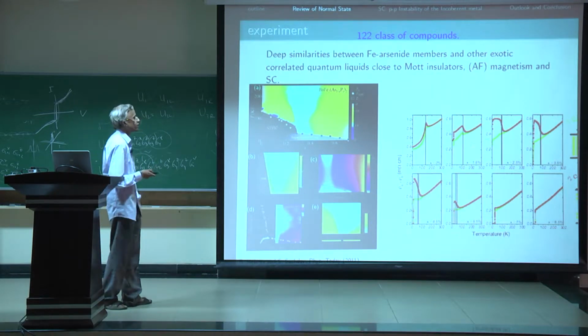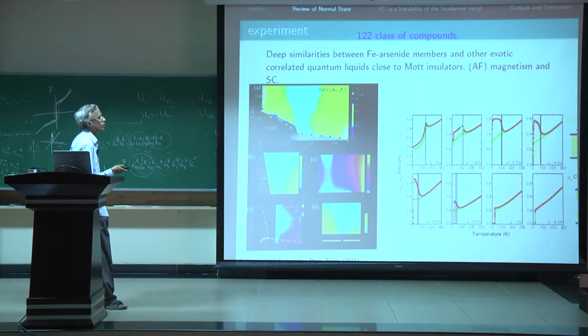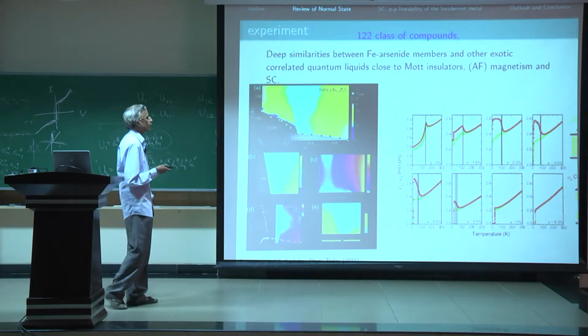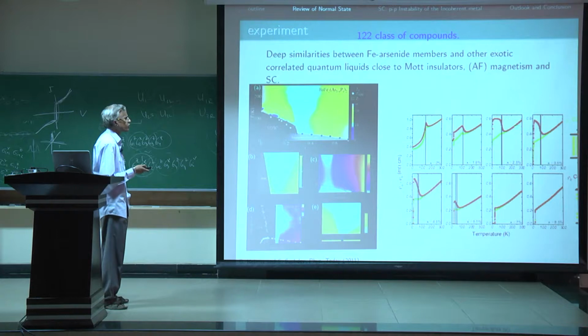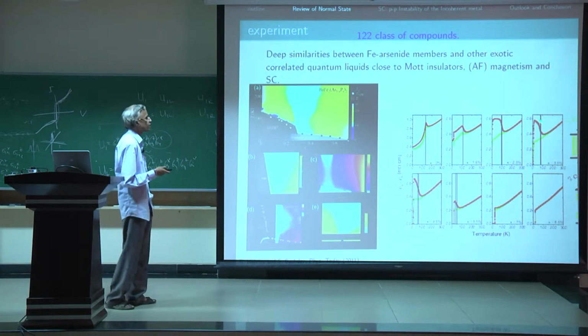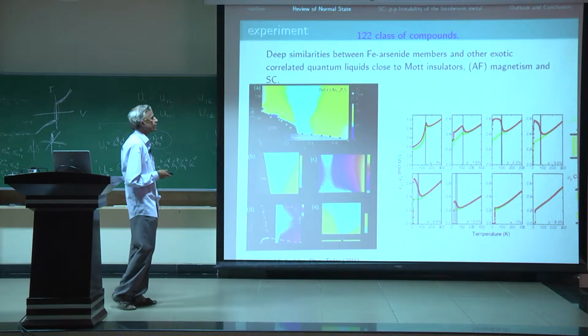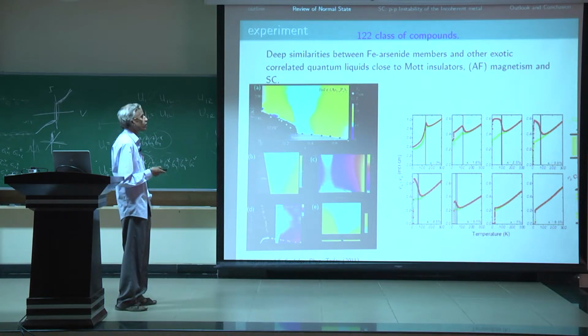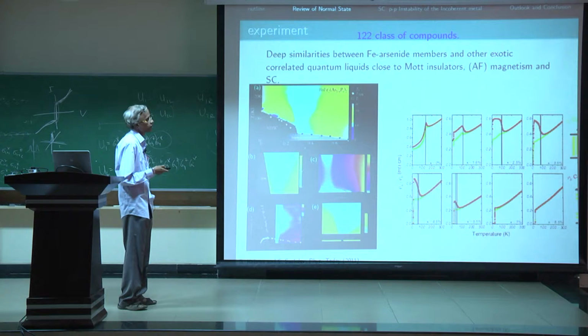In particular, what you see is that along the shorter direction, remember I told you that B is smaller than A in the orthorhombic structure, nevertheless the resistivity onset shows an anisotropy which onsets about 40 Kelvin above the structural transition, even for the parent compound. And if you look at the resistivity magnitude, it's indicative of a bad metallic state. Now this bad metallicity actually increases when you dope, in contrast to what you would expect naively.